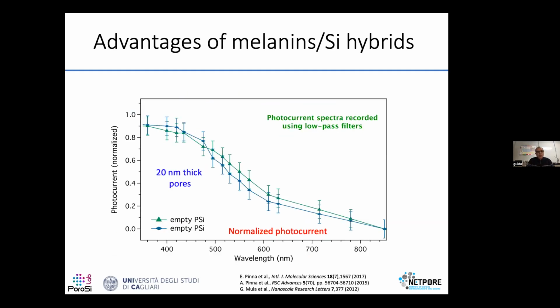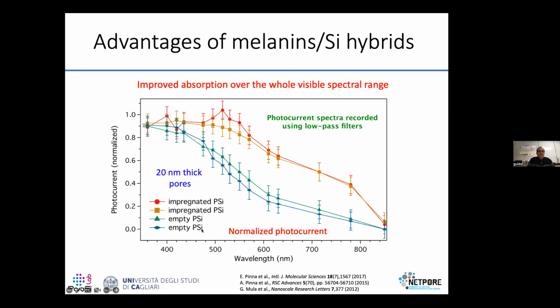First question: is the system working? Of course, the answer is yes. Here is a comparison of the normalized photocurrent obtained by measuring the photocurrent with low pass spectral filters, so your spectrum is expected to increase as you go from larger to smaller wavelength. Because if you have absorption, the range considered is the one towards the longer wavelength, so your overall photocurrent must increase if you have absorption. If you compare this, obtained on empty porous silicon, with impregnated porous silicon, you see that your absorption increases much quicker than what happens on empty porous silicon.